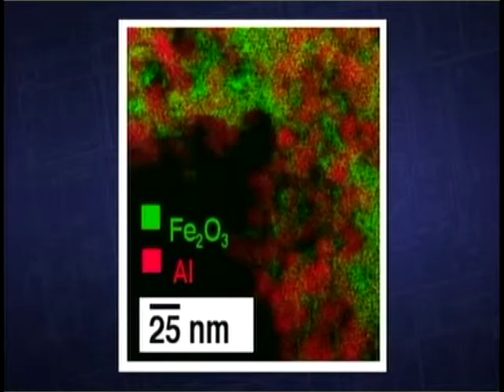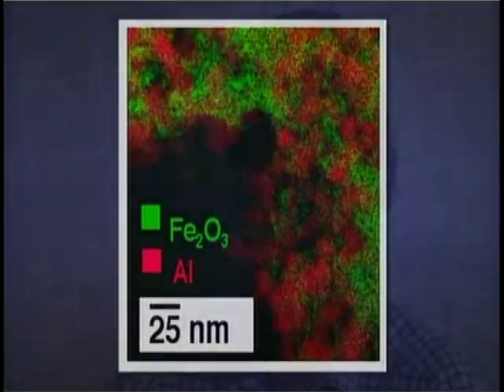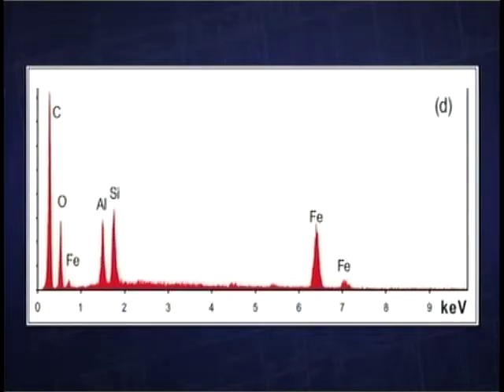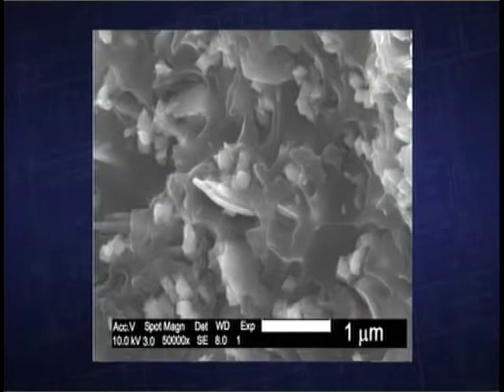First, the ingredients are much smaller, which means they react faster and are more easily ignited. The primary elements in the red material are aluminum, iron oxide, as well as silicon and carbon. The iron oxide appears in faceted grains, approximately 100 nanometers across. The aluminum appears in thin platelets, about 40 nanometers thick. It is the small size of the particles involved in this material that allows us to characterize it as nanothermite.